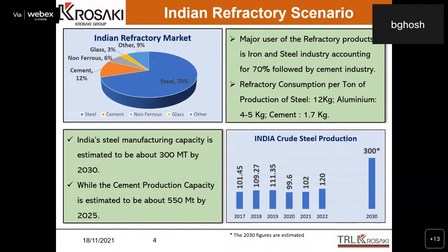And as you know, the iron and steel sectors account for 70% of the production of refractories, and refractory consumption is 12 kg per ton of steel, 4-5 kg for aluminium, and 1.7 kg for cement. On the left-hand side, in the India refractory market, 70% is accounted for by the steel sector, followed by 12% by the cement, non-ferrous sector (copper, zinc, lead, alloys), glass industry 3%, and others 9%.